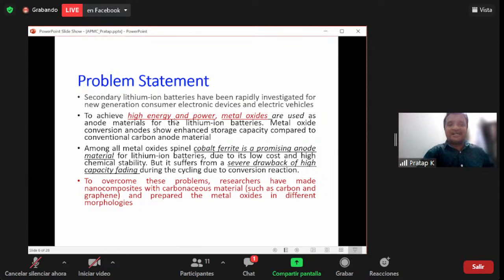To achieve high energy and power, metal oxides are used as anode materials. Currently you all know that graphite is used as anode material, and graphite has a theoretical capacity of 370 mAh per gram, and we want to enhance that capacity. For that, metal oxides are being used. Metal oxides are called conversion anodes, and they show enhanced storage capacity compared to conventional carbon anode materials. Among these metal oxides, cobalt ferrite is a promising anode material for lithium-ion batteries. Why? Because it has high chemical stability and comparatively low cost.